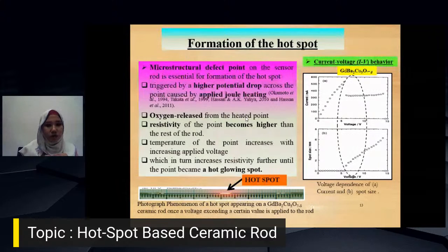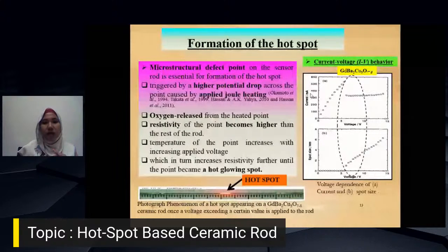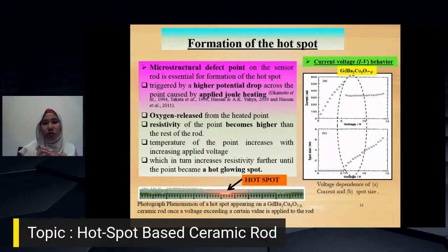On these ceramic rods, once the voltage exceeds a certain value, if you refer to this current-voltage behavior, you can see the formation of the hotspot. You have a spot size. Once the hotspot appears, what happens to the current? The output current is constant. When you increase the voltage, the spot size also increases. It shows that the glowing spot can also sense oxygen.